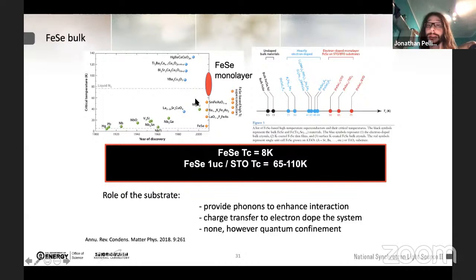And a few questions now emerge, which concern the role of the substrate. In fact, the substrate could provide phonons that can couple to the electronic degrees of freedom through electron-phonon coupling, boosting the superconductivity in iron selenide. The substrate is known also as a possible charge transfer, so it could act as an electron sink and dope our material. And otherwise, we could also be in the presence of only quantum confinement. All of these three phenomena make this system extremely interesting.